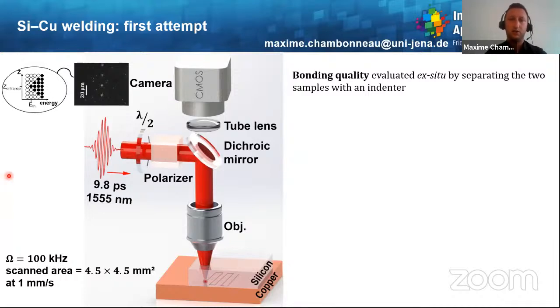So here, basically the setup is essentially the same: one laser, one target, and some diagnostics. Here, concerning the laser, the pulses are around 10 picosecond duration at the same wavelength, so 1.55 micron wavelength, for which silicon is highly transparent. Then we classically adjust the input pulse energy by means of a half-wave plate and a polarizer before the beam is focused to the interface between silicon and copper by means of an objective lens.